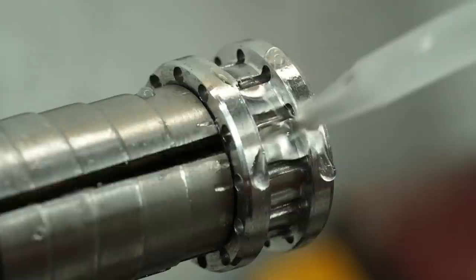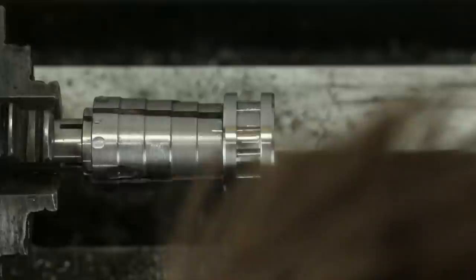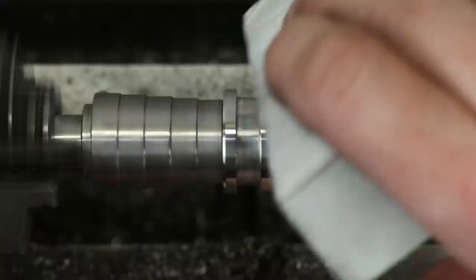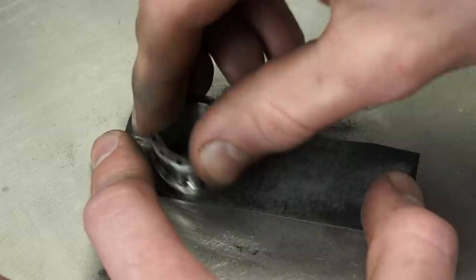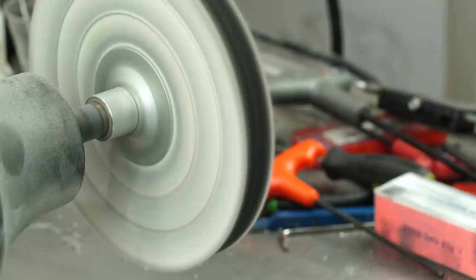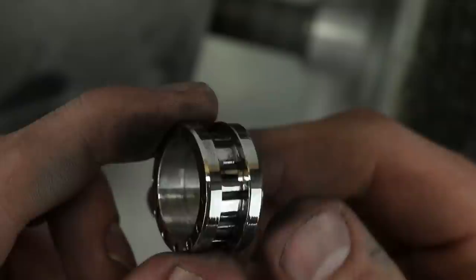For the rest of the outer sanding I use a metal block underneath my sandpaper to keep it flat — I don't want to smooth out the bevels, I want to keep them sharp. I very carefully sand the outer diameter and bevels up to about 1500 grit to get them perfectly smooth and ready to be polished. For the edges I sand them on a flat piece of sandpaper on the table. There were a bunch of burrs around the holes, so I started with rough sandpaper and slowly polished everything up. Then I polish it up — starting with a white medium polish on the left and then switching to a fine polish — leaving a nice mirror finish. Now it's time to go back into the lathe to add a comfort finish to the ring.